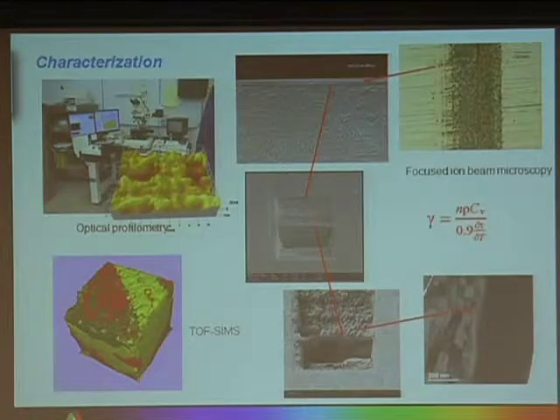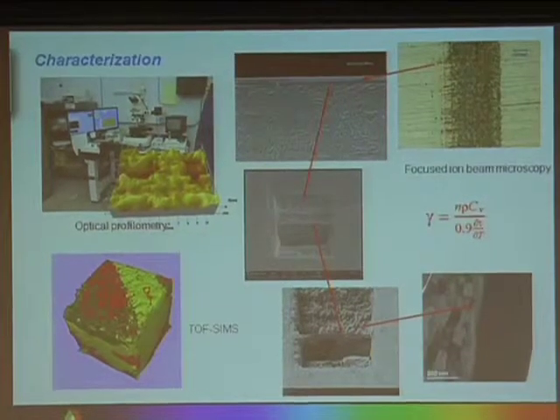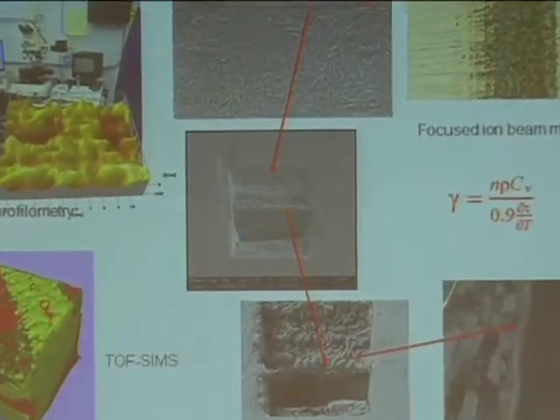In this upper photograph on the right, we're showing a wear film that was produced on a surface. You can see the wear track at the start, outside. It's a smooth surface. If you look at it in greater detail in cross-section, you can see that the near surface region is plastically deformed. If you go one step further and use the focused ion beam technique, which is kind of a backhoe, except an atomic-based backhoe, where you essentially use sputtering to mill out these surfaces, you can eventually produce a very thin film. It's about a tenth of a micron thick, 10 microns wide by about 5 microns.